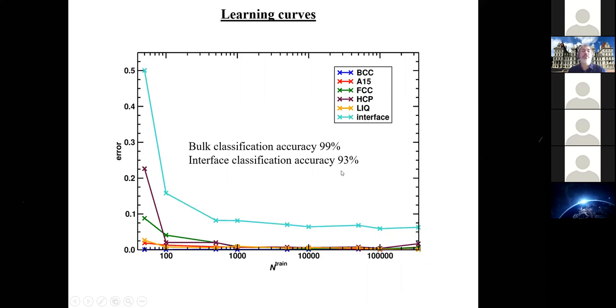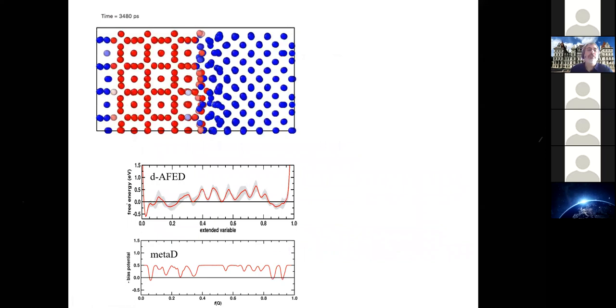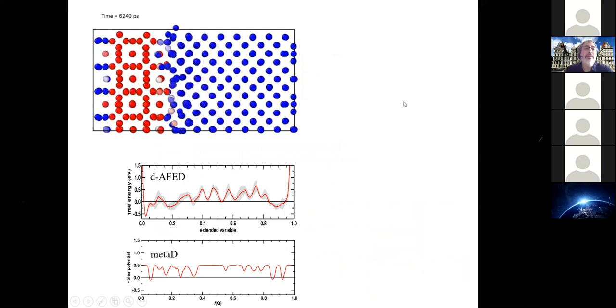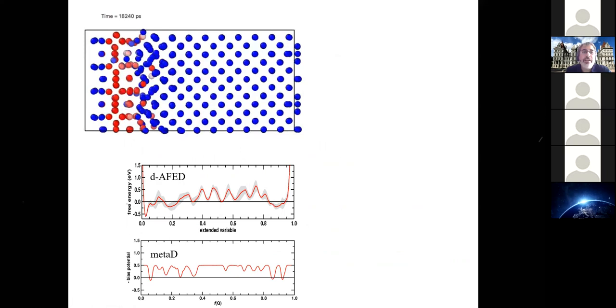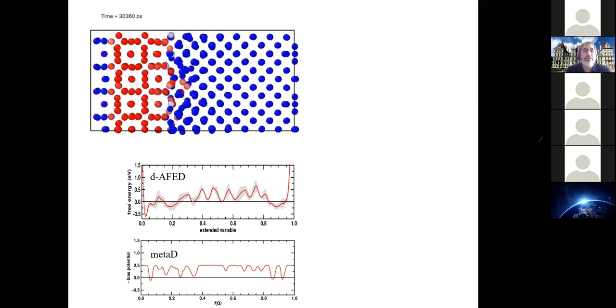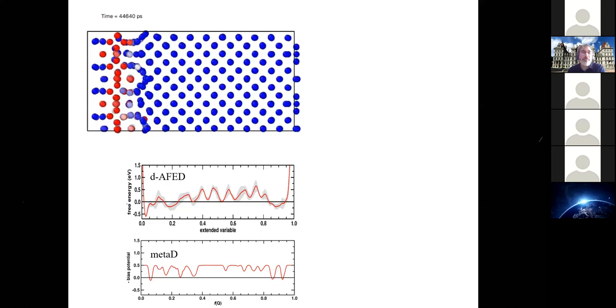And that's actually good enough for driving this transition. So I wanted to show you enhanced sampling for this interface. And you can see that the A15 phase turns into the BCC phase quite nicely by interface migration in this sample, but you can also get the interface to go back uphill and bring in the A15 phase again, all right?